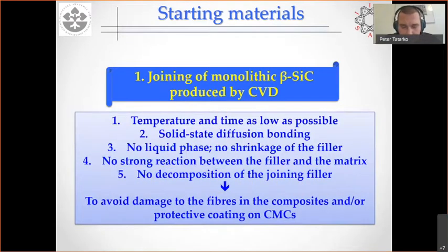There were some requirements we needed to consider before developing a new joining process. We needed to use temperature and time as low as possible. We preferred solid state diffusion bonding. We didn't want any liquid phase formation during the joining, because we wanted to avoid shrinkage of the filler, so as not to produce residual stresses in the joint. And of course, we didn't want any strong reaction between the filler and the matrix, and no decomposition of the filler. These five points were very important for us because, in the end, we wanted to avoid any damage to the fibers or the protective coating on the CMCs.